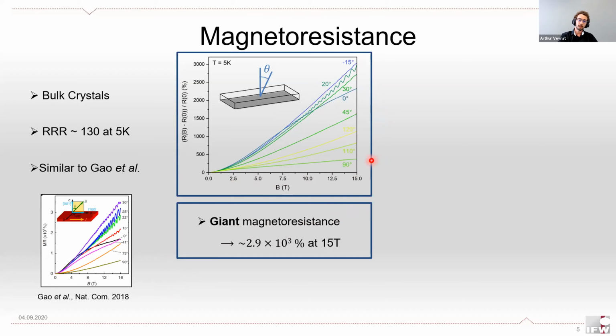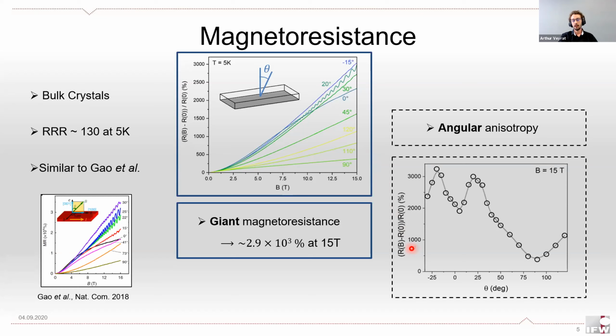And if we plot the maxima of magnetoresistance at each tilting angle at 15 Tesla, what we find is this graph, which shows that the perpendicular direction is actually a local minimum of magnetoresistance that is surrounded by two maxima, at plus or minus about 20 degrees.